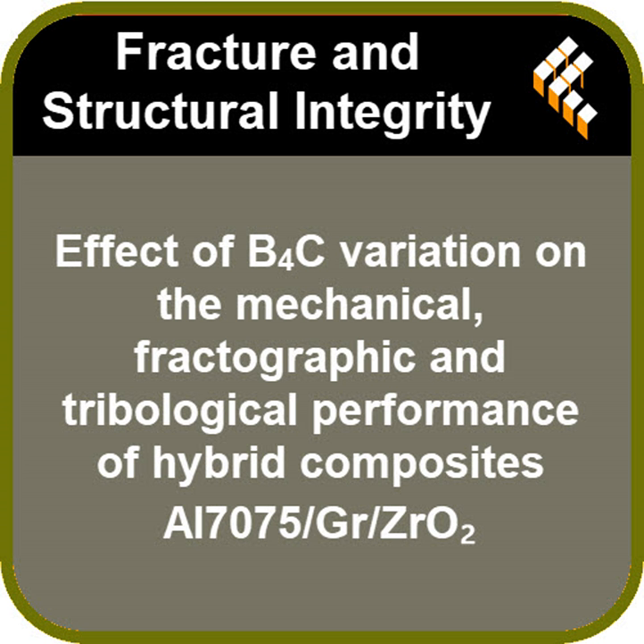Okay, so let's get into this study. They're reinforcing the standard AL7075 matrix with not one, but three different things. We've got fixed amounts of graphite, that's GR, and zirconia, ZrO2. And then they vary the main event, which is boron-carbide, or B4C. And the whole point there is what we call synergistic strengthening. Yeah. They're blending these hard ceramics, the zirconia and the boron-carbide. All right, those bear the load. And then you have the graphite, which is a solid lubricant to minimize friction.